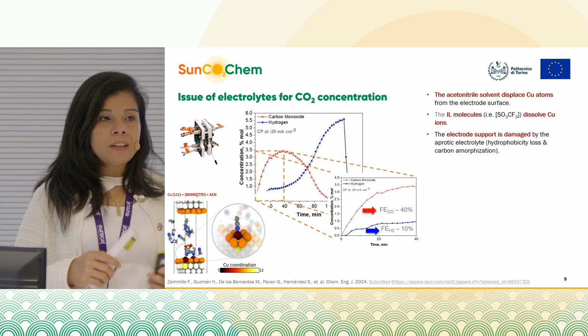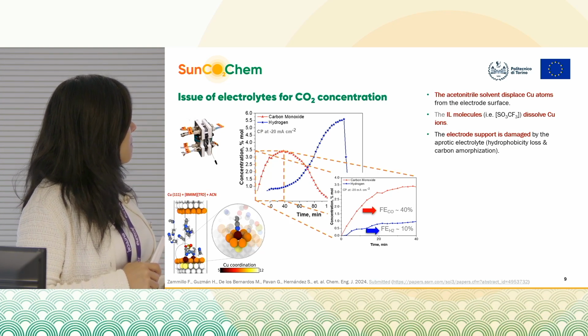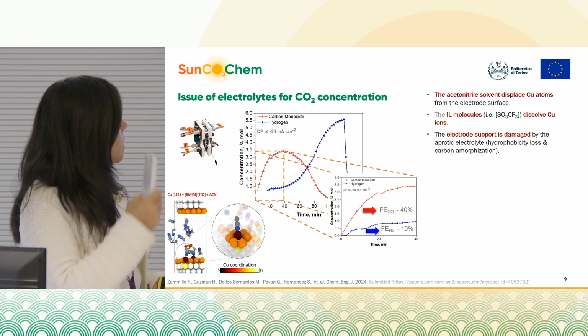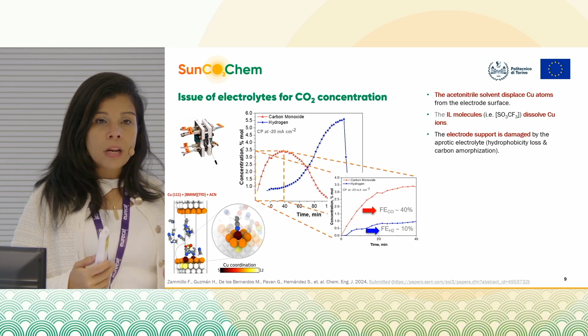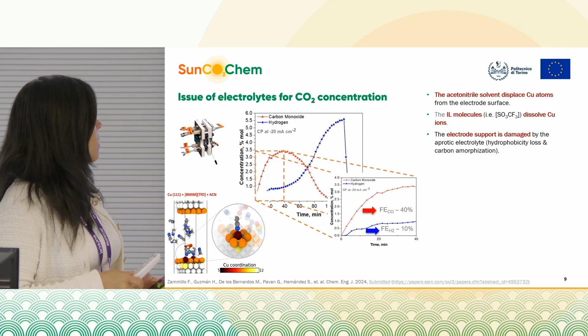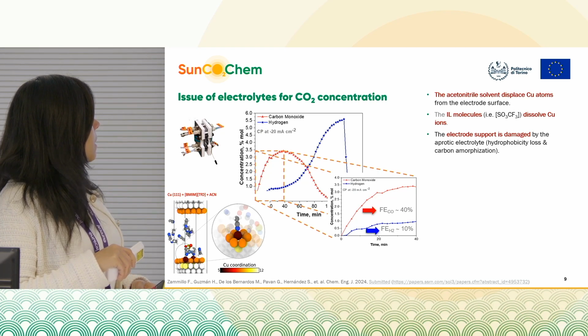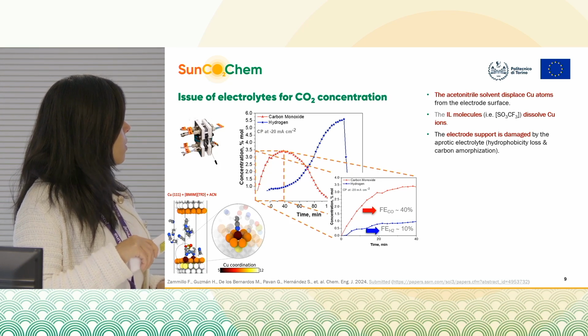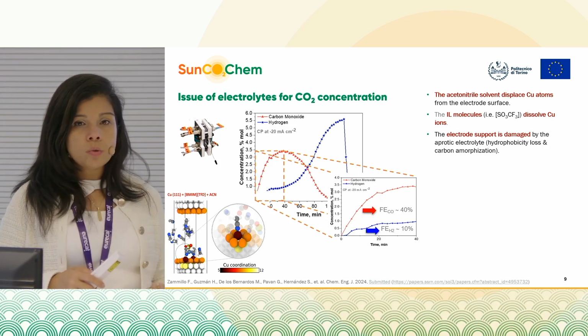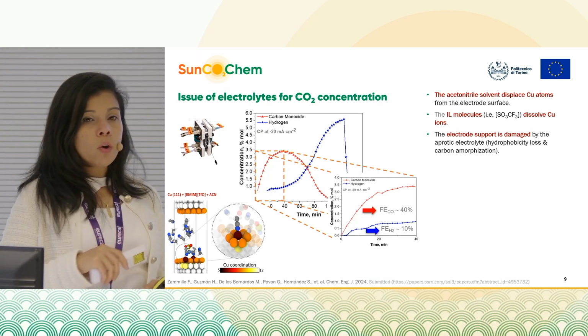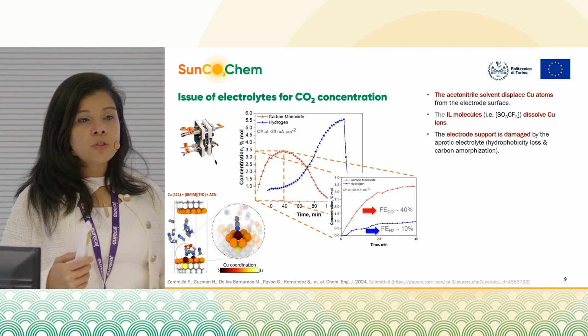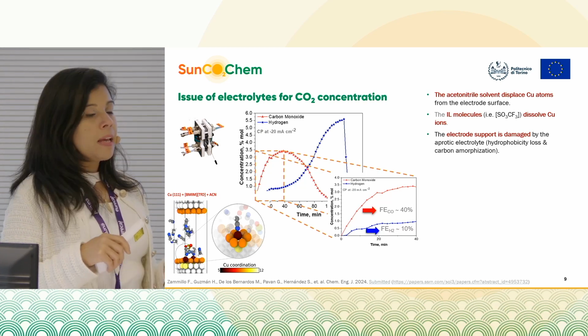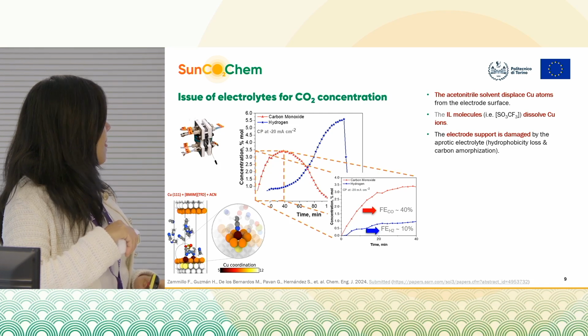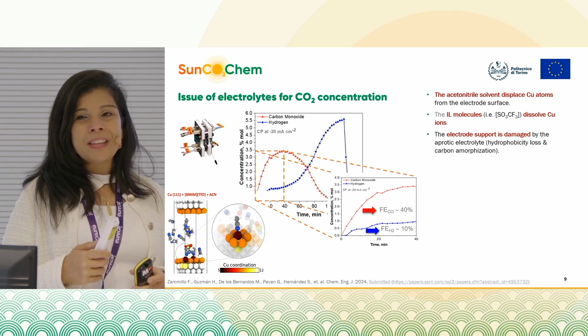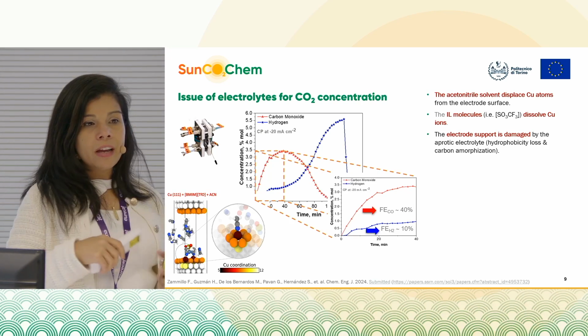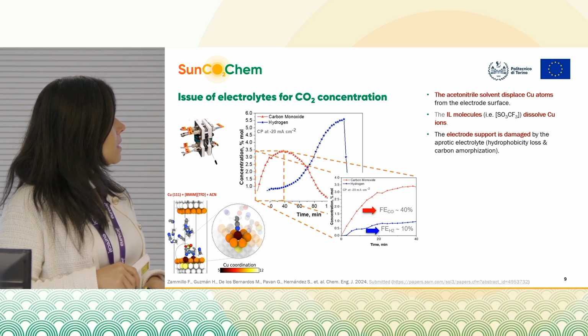So the results that we obtained in this long path trying to look for a better system, better catalyst, starting with ionic liquids: we observed that using these gas diffusion electrodes based on a carbon-based gas diffusion layer, we obtained some instabilities after some time regarding the production of CO and an increase of the evolution of hydrogen. So we identified the issues related to these phenomena with some molecular dynamics simulations, and we observed that actually this organic solvent that we were using, acetonitrile, basically displaced the copper atoms from the surface of the electrode, and then we have a very good affinity with the triflate anions in the solution that basically dissolve the copper surface, dissolving the copper species in the electrolyte.